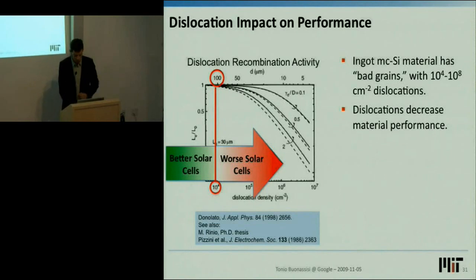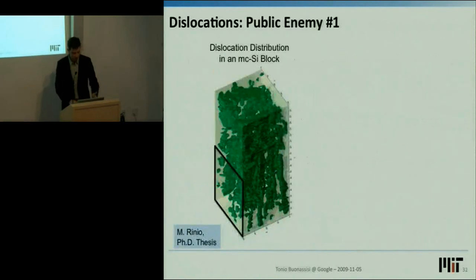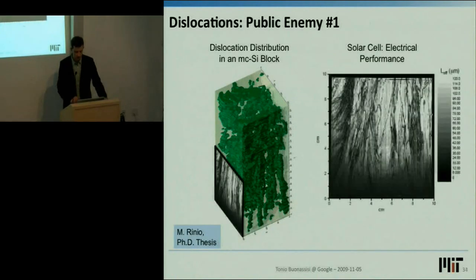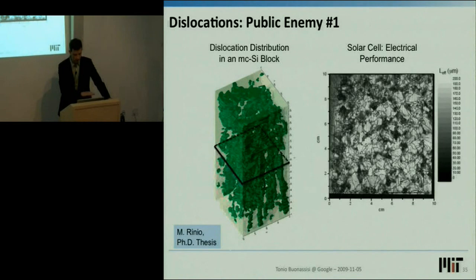because the probability that some electron inside the material will encounter a defect is very, very low. Now, let's take a wafer out of a vertical slice, shown here by this little box. And if we scan that region using an electrical performance mapper, we realize that there are some really bad regions caused by regions of high dislocation density. Likewise, if we take a wafer in the cross-section, as we're apt to do when we actually produce a solar cell, we find that the wafer itself has a checkerboard-like pattern of these bad regions together with the good ones.